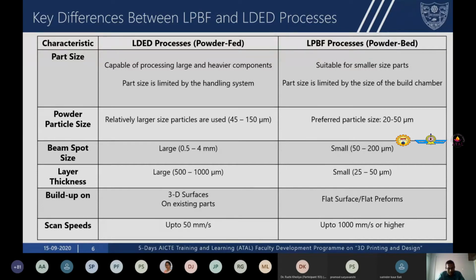Now, when you look at the powder particle size, directed energy deposition uses a larger powder particle size that varies from 50 to 150 microns, whereas in the powder bed fusion process, you go with a very much smaller particle size from 20 to 50 microns. The spot size of the laser beam used is large in the case of directed energy deposition. It's about 0.5 to 4 mm, and is much smaller in the case of powder bed fusion, which is from 50 to 200 microns. The layer thickness is again much larger in directed energy deposition, from 500 to 1000 microns, and much smaller in the powder bed fusion process.